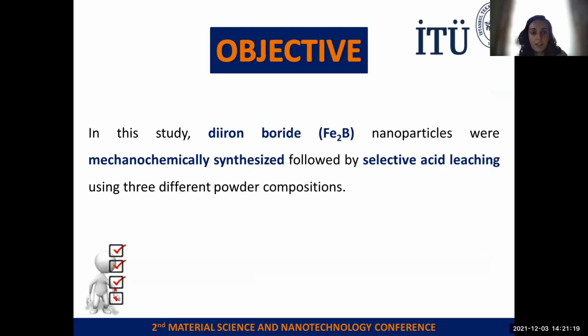discussion. Okay, the objective of our study: iron boride nanoparticles mechanochemically synthesized, followed by selective acid leaching, using three different powder compositions, three different powder mixtures. The main objective of this study is to synthesize iron boride nanoparticles without any impurities using solid state reaction.